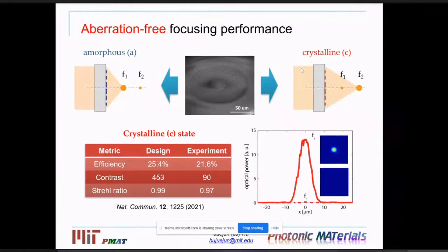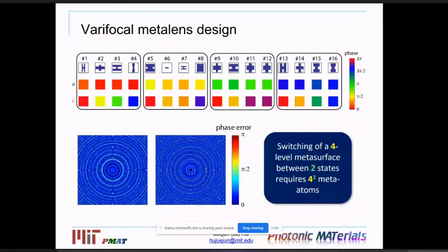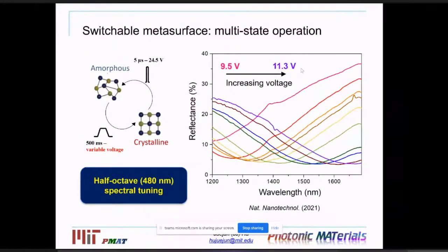I have a question. When GSST goes from the amorphous to the crystalline state, when you give an electrical pulse or whatever, what is the crystalline phase actually? What phase does it crystallize into? For GSST, the crystalline phase is cubic. It actually has two crystalline phases: one is a metastable cubic, the other is hexagonal. Very similar to the parent compound, GST, germanium antimony telluride. For switching purposes, we are mostly talking about the cubic phase, because it's the phase that's amenable to fast switching.